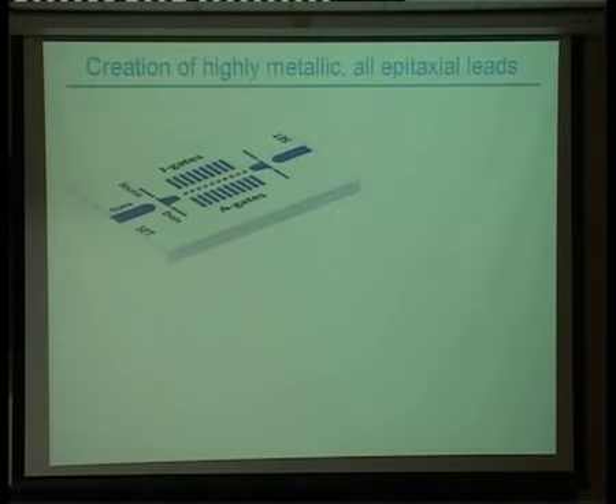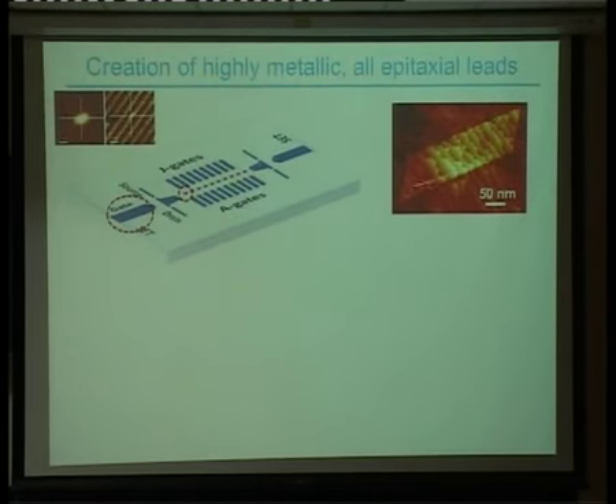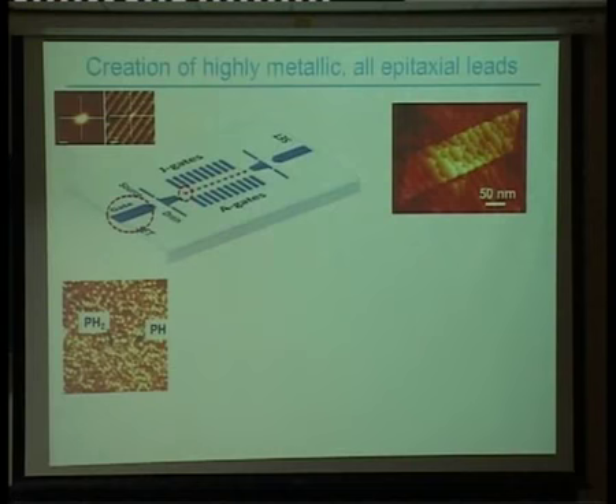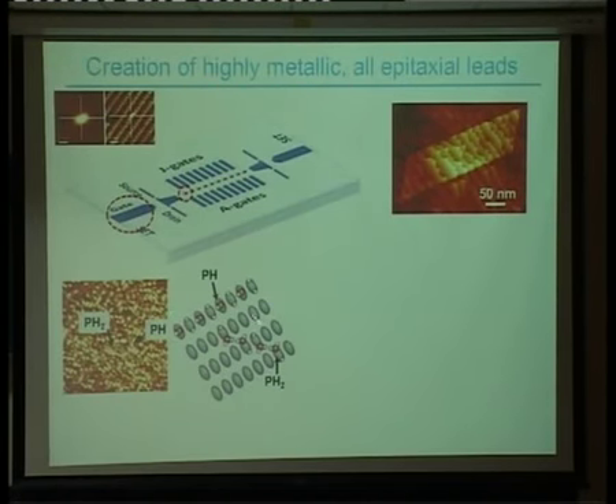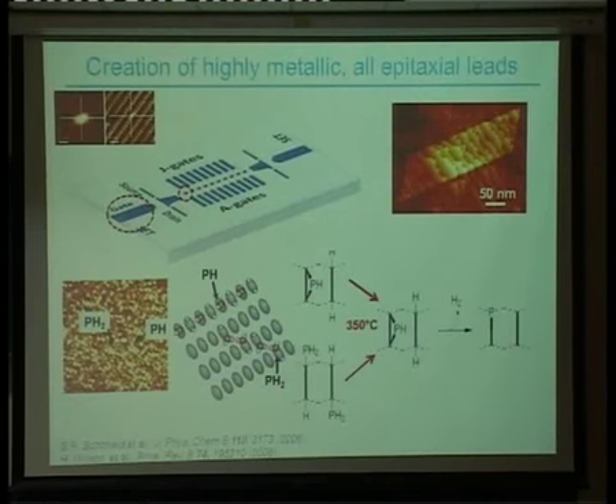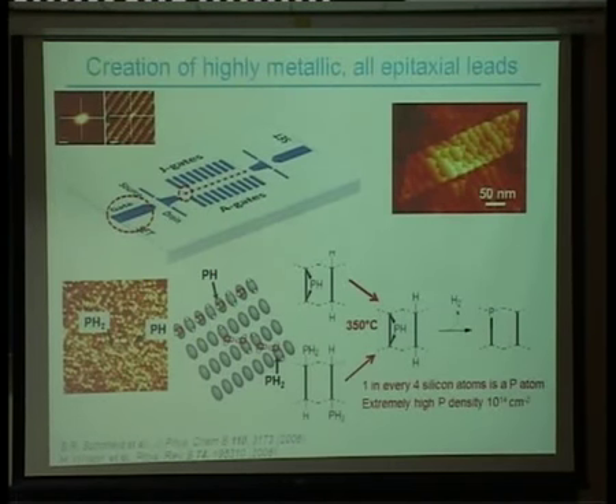That's how we get our qubit states in here, but we also, as I mentioned before, at the same time, align these gates on the surface to that phosphorus atom. And we do that essentially by opening up large regions of the surface and phosphine dosing those at exactly the same time. The critical part of this is understanding the chemistry to get a very saturation dose surface so that when we heat this surface up, we typically find that 1 in 4 of the silicon atoms is replaced by a phosphorus atom. So this is an incredibly high density, and this was, I guess, unexpected when we started. We didn't realize we would get such high densities on these systems. It basically means that the average separation of the phosphorus atoms is less than 1 nanometer, and the Bohr radius is 2.5 nanometers.